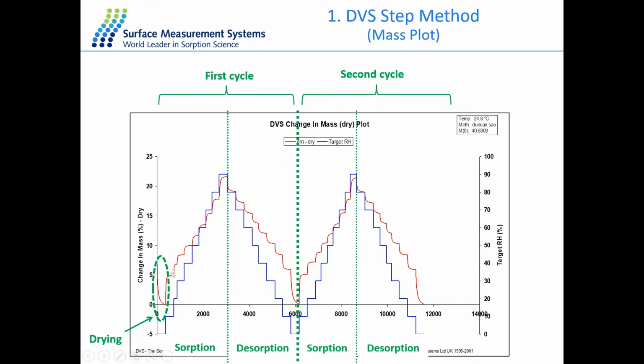And then we can get the equilibrium state at each stage, and those values will give us the equilibrium moisture content of the material at each relative humidity. As for this sample, as you can see, at 90% RH, the mass change is around 20%. That means the sample has really good affinity with water. And that water could be either on the surface, or it can also go to the bulk of the material. During the second cycle here, the moisture sorption at 90% RH is almost the same level as the first cycle. That means it's a totally reversible process. So it can go back to the same level in the second cycle.